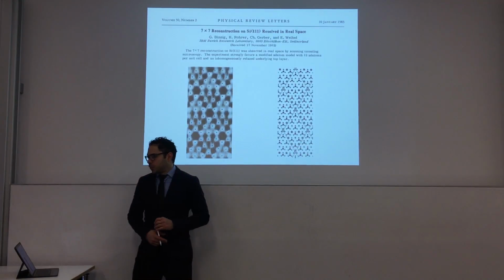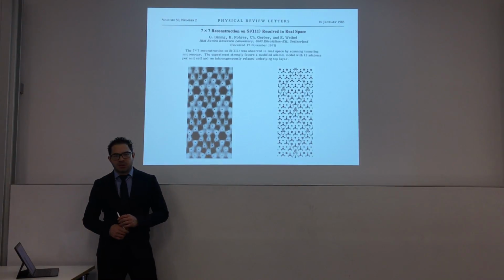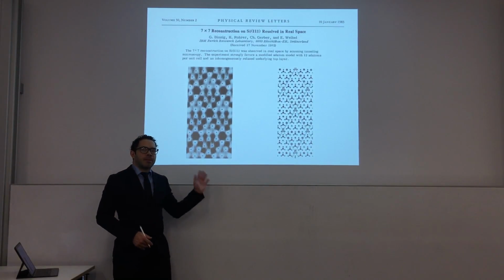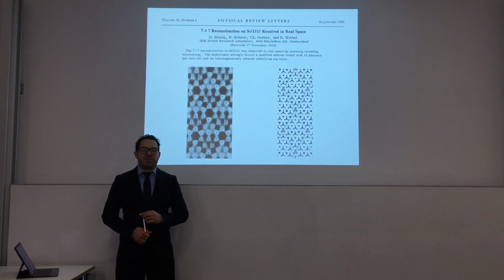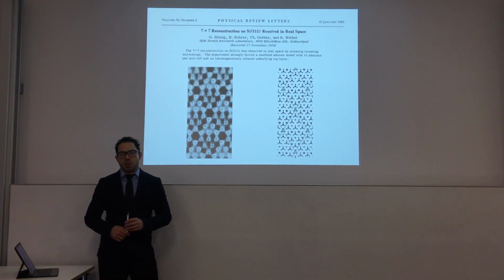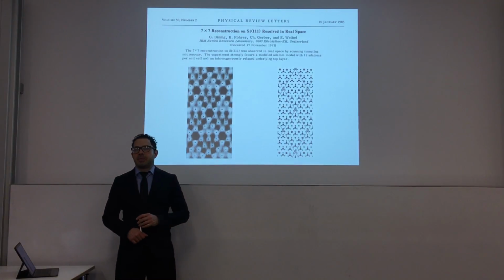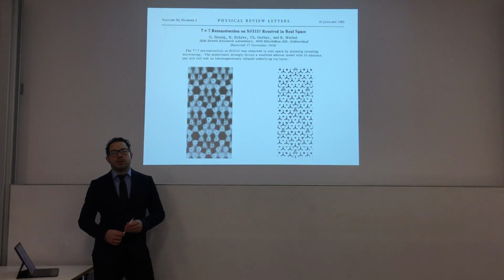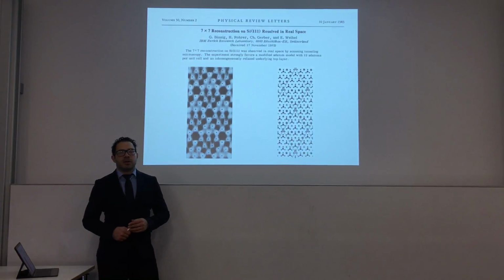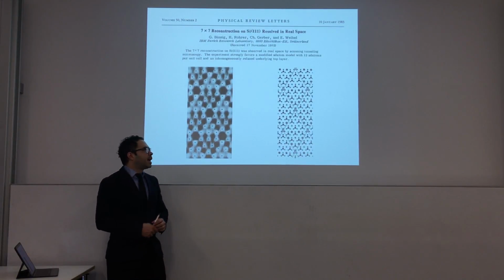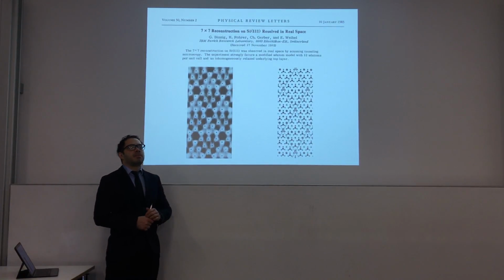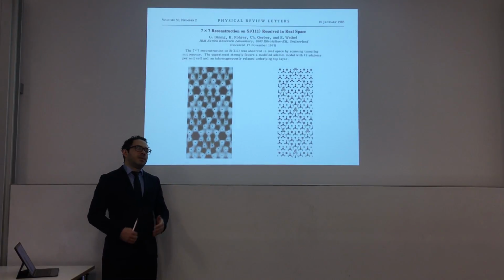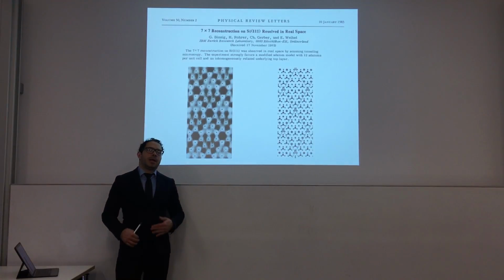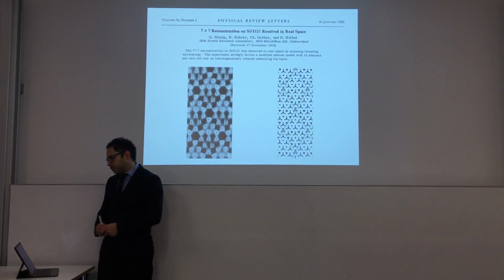One of the most representative examples of the application of scanning tunneling microscope was precisely one of the first papers on this, and it's a demonstration of the reconstruction of silicon 111. At this time, it was a very high-profile topic to provide an experimental demonstration of how this reconstruction occurs. And these guys, the inventors of STM, did actually that. They used STM to map silicon 111 with atomic resolution and to confirm the 7x7 reconstruction.